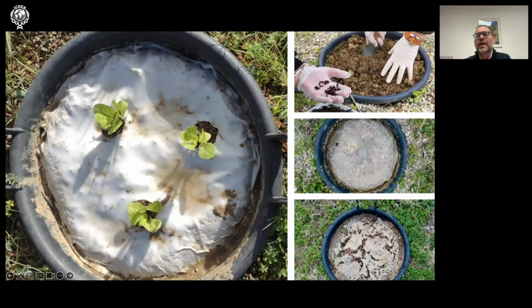As you can see on the right side, at the bottom of the screen, our films start to degrade after the cultivation of the lettuce. This happened, if I remember well, after 50 days of our experiment. So this confirmed that our films are really biodegradable, but also confirmed that we need to improve our mulching films to allow the cultivation of more crops, because they start to decrease only after 50 days.